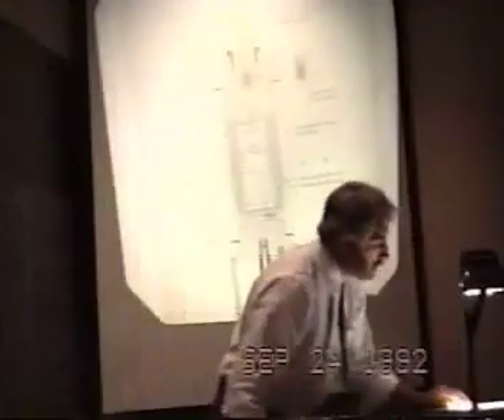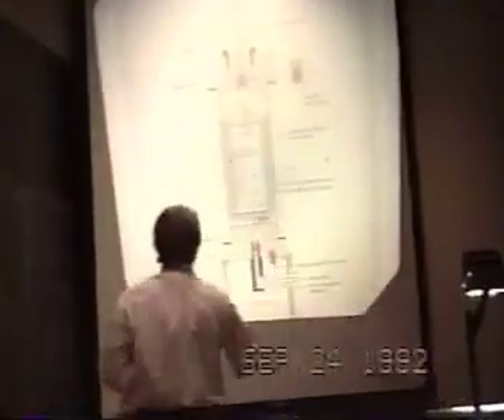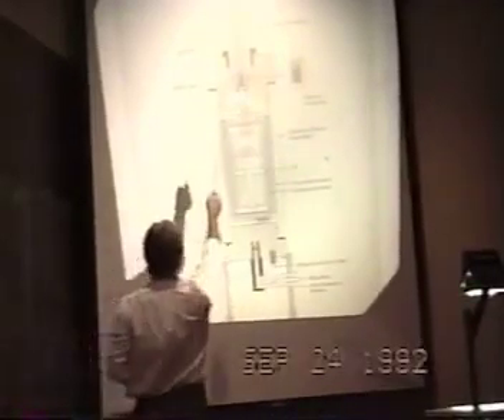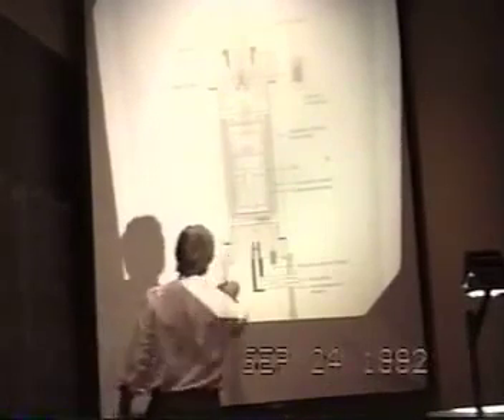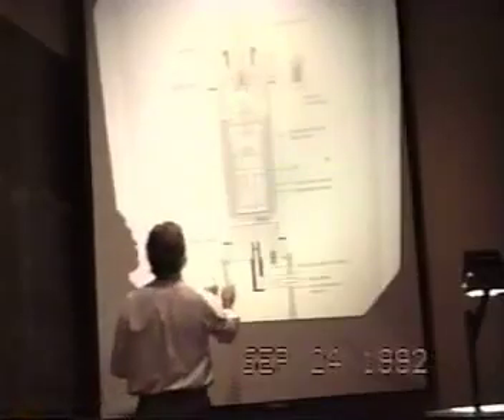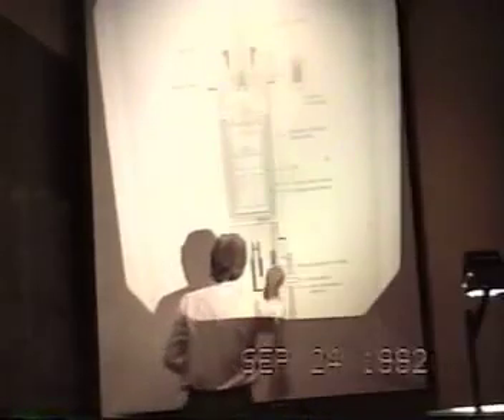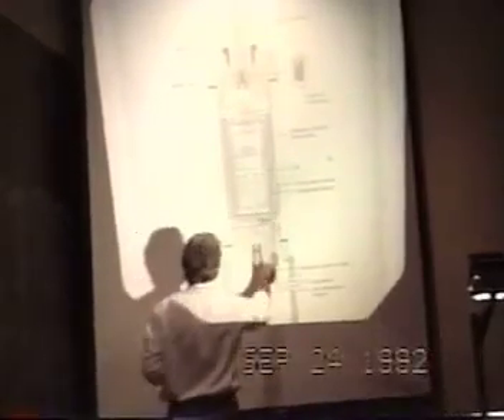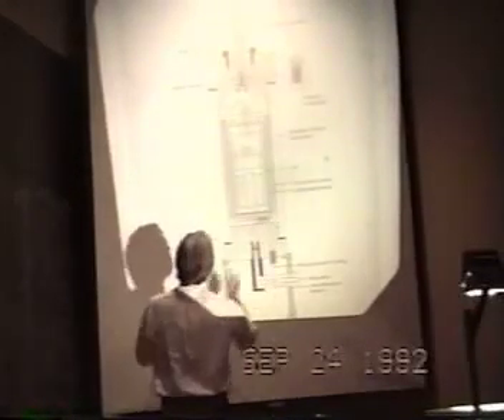If you look at a slightly greater detail of the electrochemical cell, here is the same device with the feet which maintain it above the bottom of the bath. 2 inlet sensors in this manifold. I'll show you the outlet manifold in a second. The electrochemical cell is placed with the heat transfer fins in the radial direction so that the flow comes from the bath, past the cell, through the annular space between the cell and this evacuated silvered dewar, maintaining the constant temperature boundary, and past the 2 outlet temperature sensors.